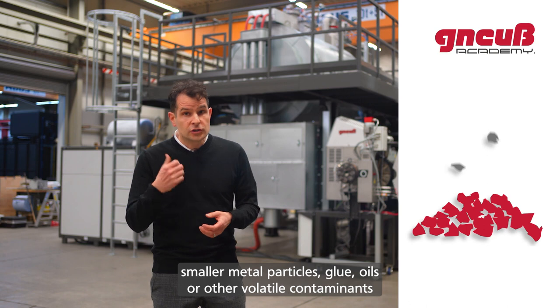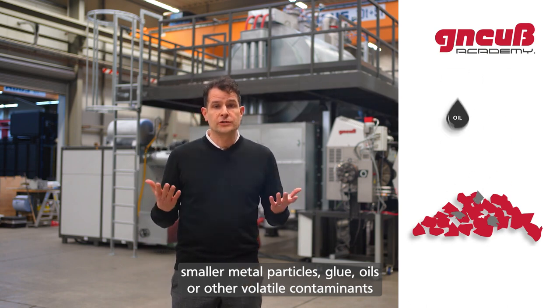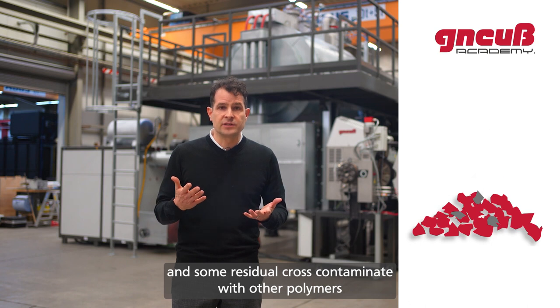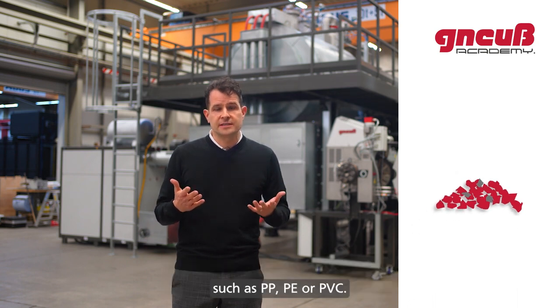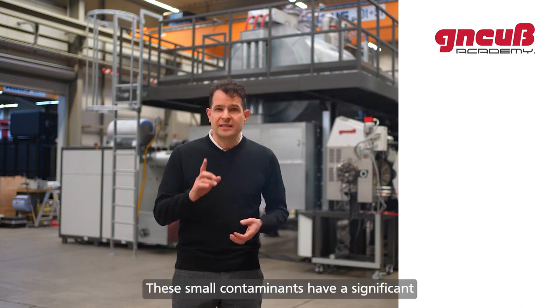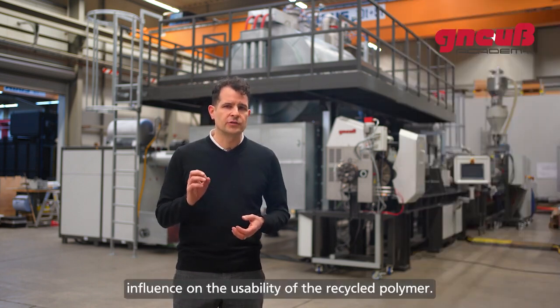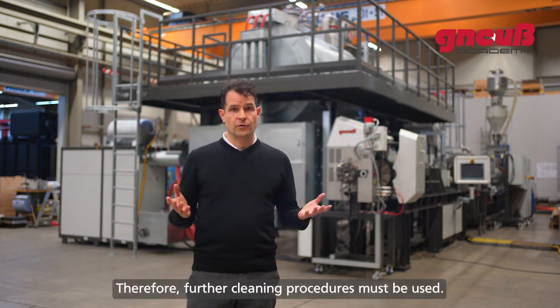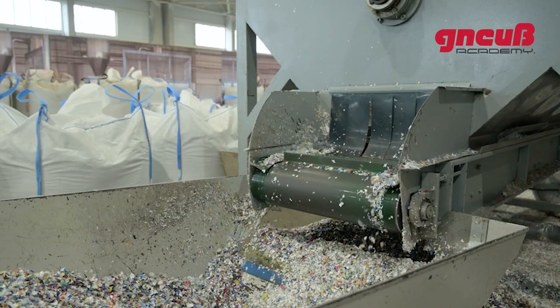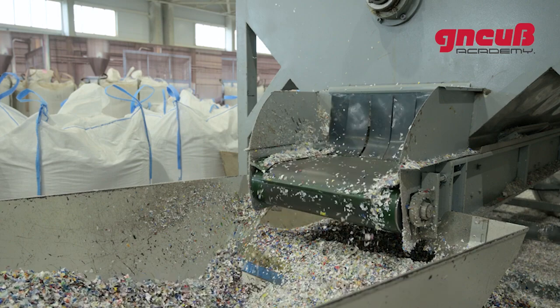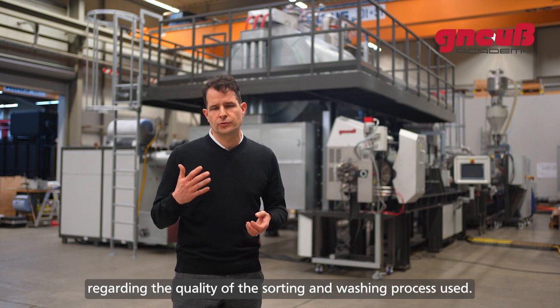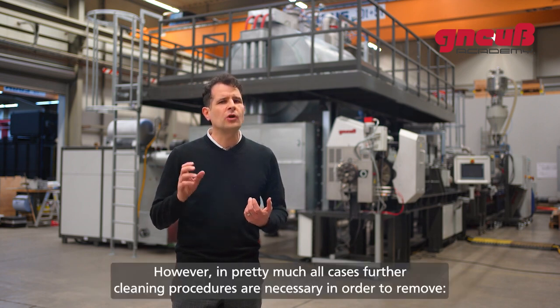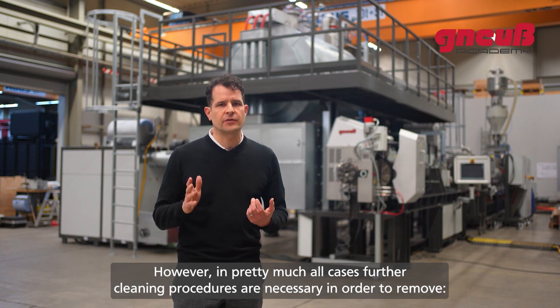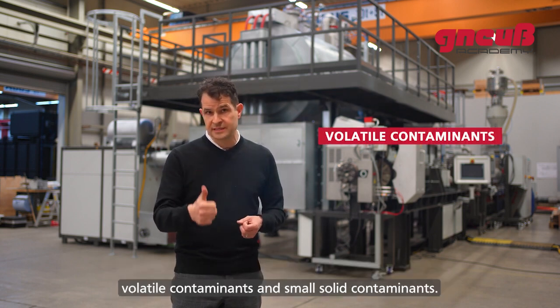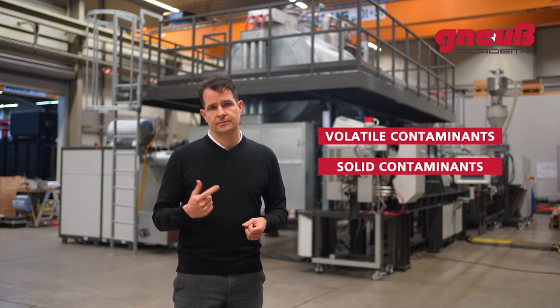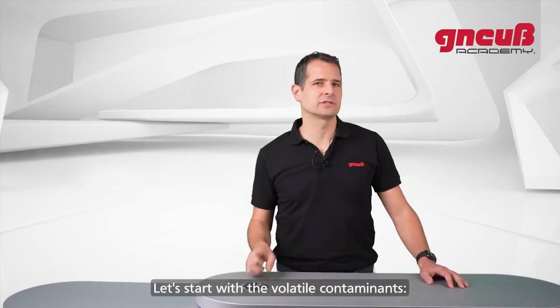Typical leftovers are smaller metal particles, glue, oils or other volatile contaminants, and some residual cross-contamination with other polymers such as PP, PE or PVC. These small contaminants have a significant influence on the usability of the recycled polymer. Therefore, further cleaning procedures must be used. Obviously, you can imagine that there are big differences regarding the quality of the sorting and washing process used. However, in pretty much all cases, further cleaning procedures are necessary in order to remove volatile contaminants and small solid contaminants. Let's start with the volatile contaminants.